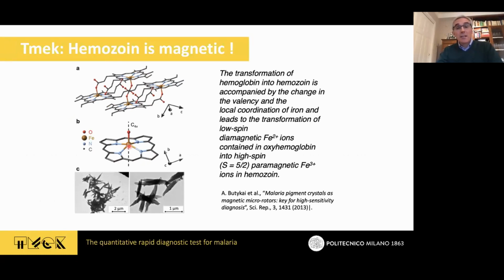Which is not a high spin state. In this case, the magnetic moment is 0. But when you oxidize it, you turn it into the iron 3+ oxidation state, in which the spin is 5/2. This is a high spin configuration, and that's why you get paramagnetic behavior. And if you have something which is paramagnetic, obviously that's the basic building block for the possibility of manipulating this kind of crystal. And this is really the basis also for the diagnostic methods employed so far.